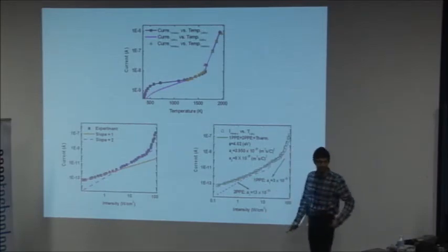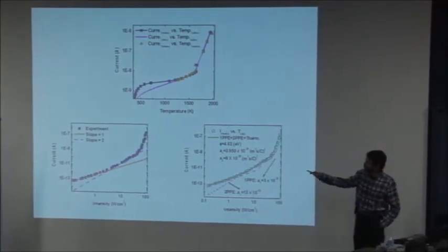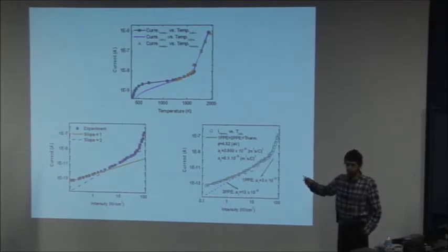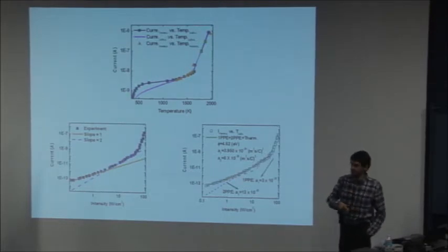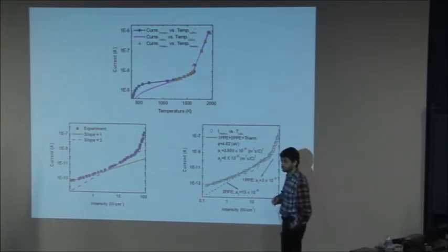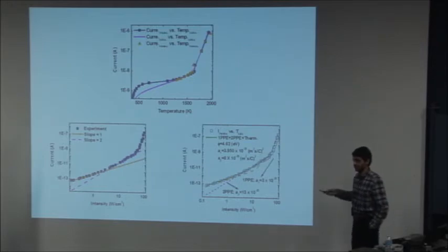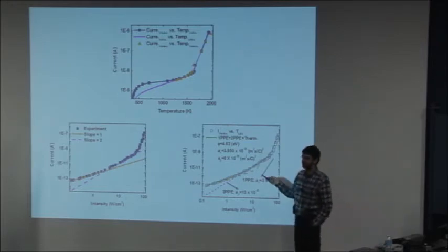under photoelectric conditions. And this was interesting to us because this curve that you're seeing here, you find it in the literature from the 1930s, the so-called Fowler-Dubridge model of photothermionic emission. But it was more of a theoretical curve.